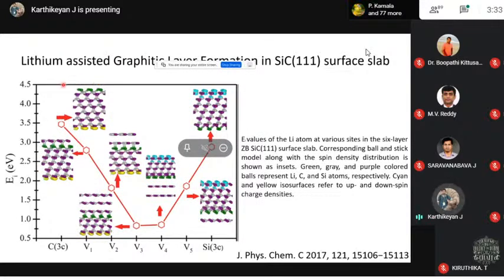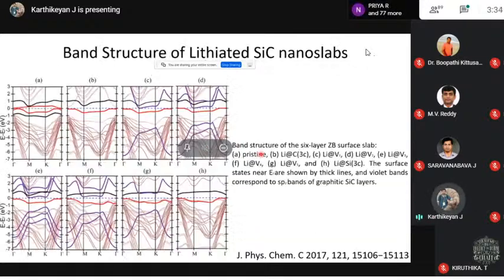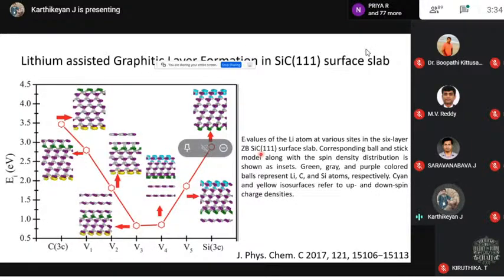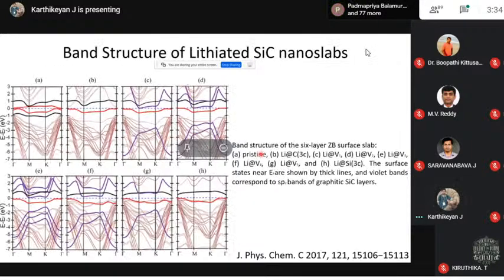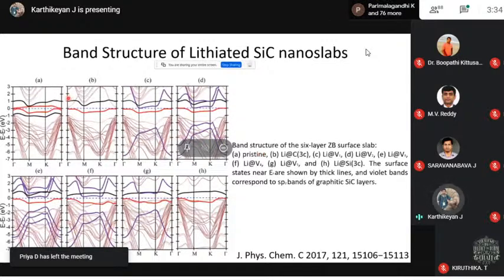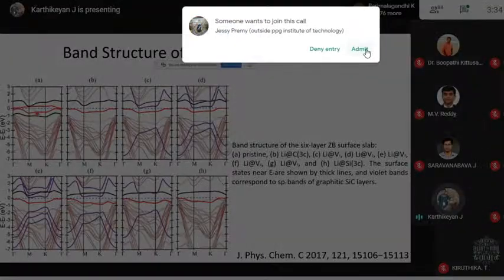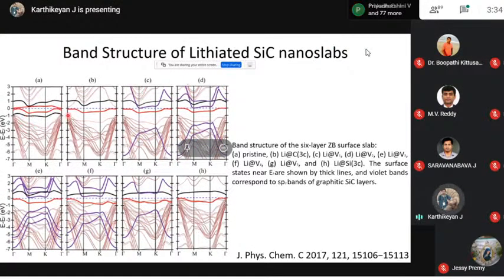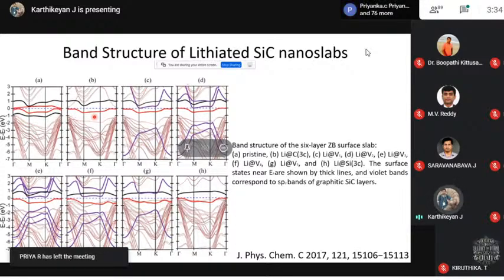So let us see. We are going to take this order. Based on these energies, we are going to add more and more lithium to this silicon carbide, and we can calculate the capacity also. And let us understand what is happening in the lithiated structure. As I told you, this is for the pristine surface slab. There are surface states. But when you add a lithium, you can see that one band, the black one, is disappearing, because we have added a lithium which donates 1 electron to the surface atom. That quenches the magnetic moment, that kills the surface states.